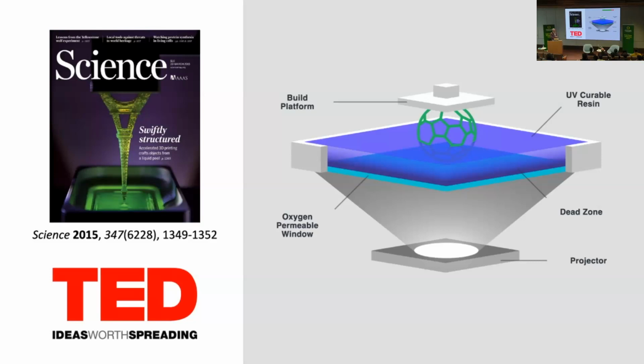Light's going to pass through a window at the bottom of this reservoir, a very special window, a window that's not only optically transparent, but it's permeable to oxygen. And those of you that are familiar with free radical polymerizations know that oxygen is an inhibitor of free radical polymerizations. It inhibits the solidification process, if you will, that light is imaging into the polymer. And what's going to happen is that this build platform will lower into this reservoir, we'll get very close to the window, it'll be a gap, maybe 100 microns, and we'll start illuminating with light, and it'll trigger the pattern forming chemistry that takes place.